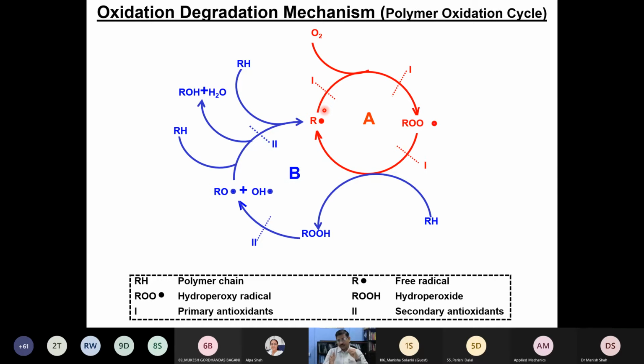However, at one point of time, our cells' rate of growth is much higher than the degradation or depletion rate. As a result, you may not see aging in a human up to 50 or maybe 55. Afterwards, this process will dominate. So the free radicals, upon interacting with the free oxygen available in the water, or the dissolved oxygen available in the leachate, end up producing another aggressive free radical, called a hydroperoxide. Then the hydroperoxy radical interacts with the polymer chain, and it will dissociate into hydroperoxide, and then this hydroperoxide will dissociate again into a free radical and OH minus. So once this process starts, it is a cyclic process. This is called the primary oxidation cycle. The outshoot of that is called the secondary oxidation cycle.